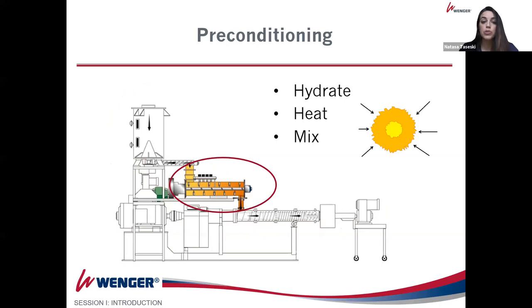For most of the textured proteins, there's a considerable advantage of having preconditioning included in your process. And we'll talk about that a little bit. So the function of the preconditioner is really to hydrate, heat, and mix ingredients. And primarily it is really to hydrate and mix. Because when you're dealing with materials that may have different water uptake or may have some variation in particle size that may interfere with the hydration rate, having a preconditioner, you're able to ensure that you have even penetration of moisture into the particle, into the granule.